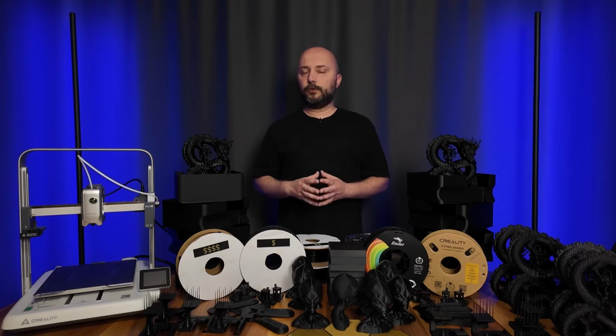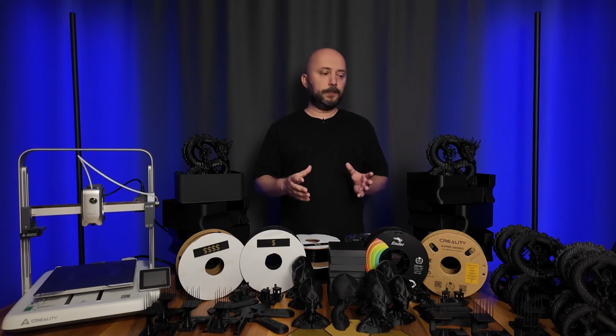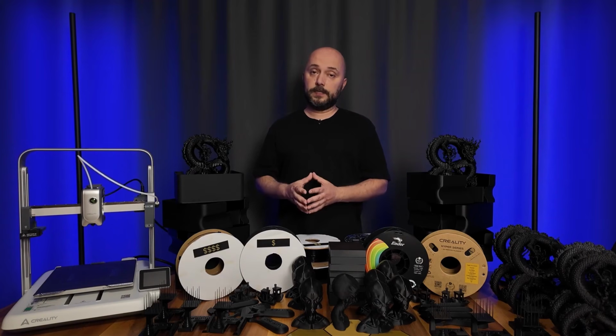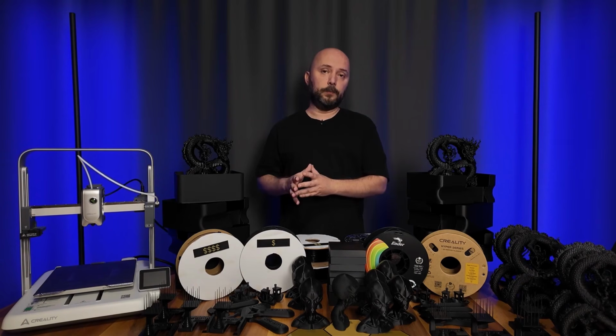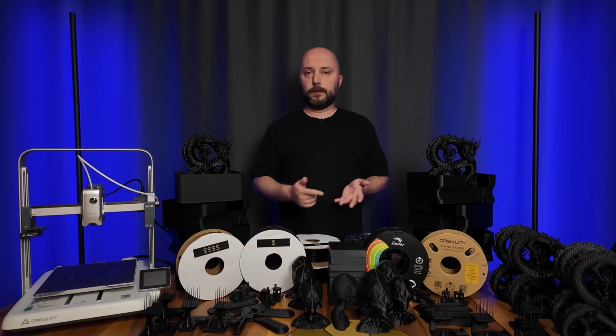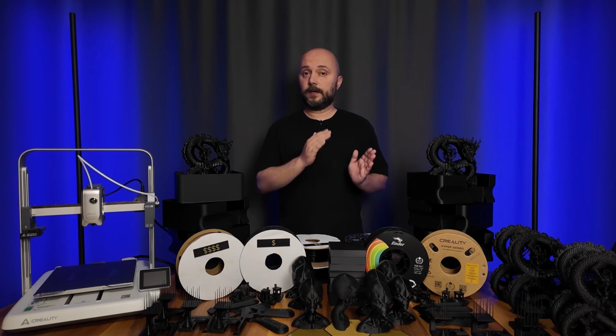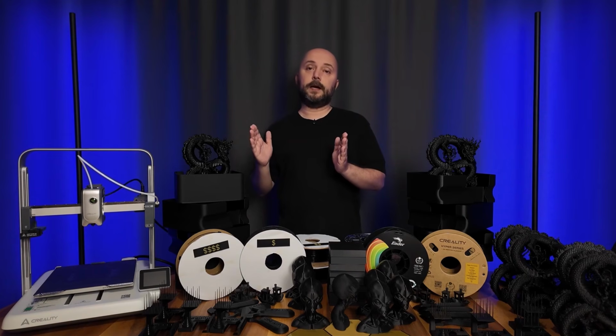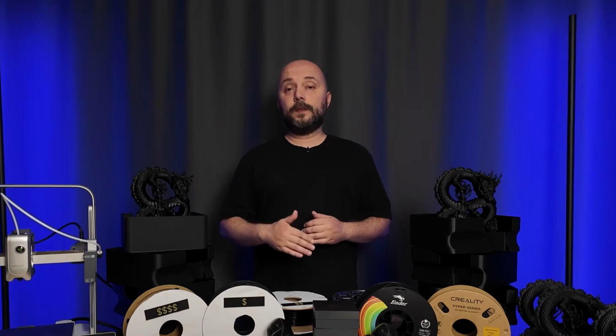I won't be giving a score regarding the diameter consistency of the filaments because most of them were quite successful. Both the diameter and ovality consistency of the filaments turned out to be very good. The only one I wasn't satisfied with here was the expensive filament. Why? It stayed below 1.70. In other words, we needed to be between 1.70 and a maximum of 1.80, so even if it was on the borderline, in my opinion, it doesn't deserve a point.